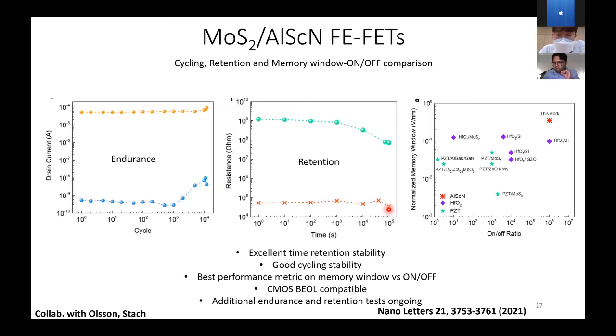Now, in terms of transistor-based memory, there are two major metrics that you want to compare. One is the memory window, another is the on-off ratio. In memory window, we are normalizing it because everybody makes different thicknesses of the dielectric. So you can see that on the normalized memory window and on-off ratio metrics, this 2D AlScN FE-FET is actually better than anything else that is out there, right? And this number has actually been pushed even further. We have unpublished data where we have 10 to the power 8 on-off ratio, and the memory window normalized is still similar. So we have been able to push this point at least 2 more orders of magnitude this way.